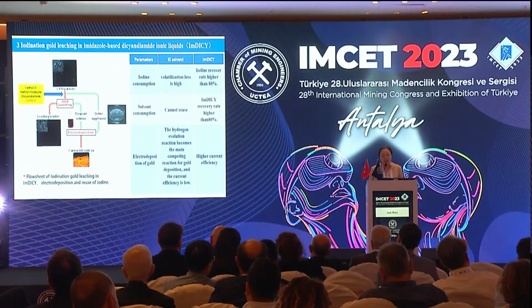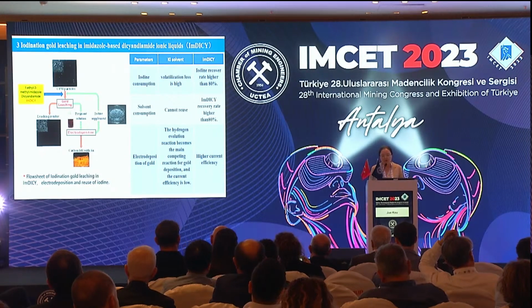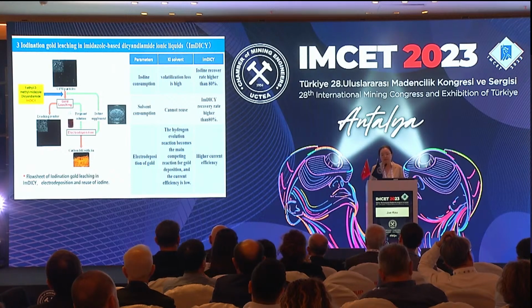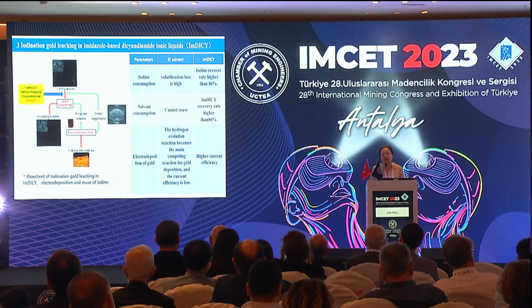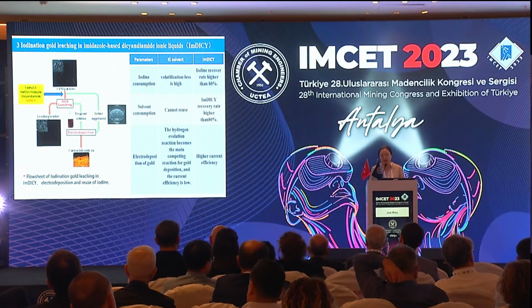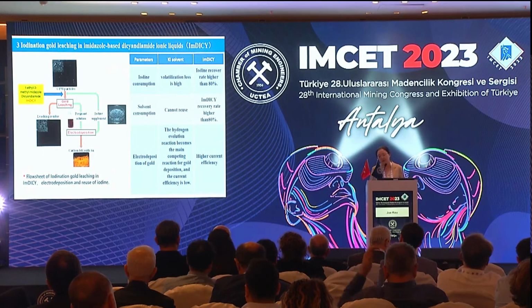In this table, we compared the parameters of water solvent gold leaching and ionic liquid solvent gold leaching. For water solvent, the volatilization loss of iodine is quite high, but for the ionic liquid, the iodine recovery rate can reach 90%. And for solvent consumption, the water solvent cannot be reused. But the ionic liquid we can reuse by reusing the anolyte. The rate of recovery also reached higher than 80%.